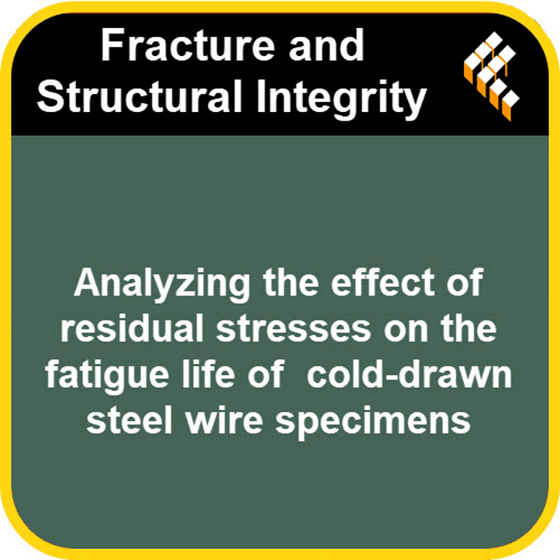Potentially, yeah. And they even did this extra check with yellow markers, groups A and B. That was interesting. They marked the wires to see if it mattered which way up the wire came off the original manufacturing spool. You know, did it have a top or bottom from coiling? Yep. The results for Group A and B were, as they put it, quite similar. So that initial orientation didn't seem to play a role. Good to rule that out. Always good to check those variables.